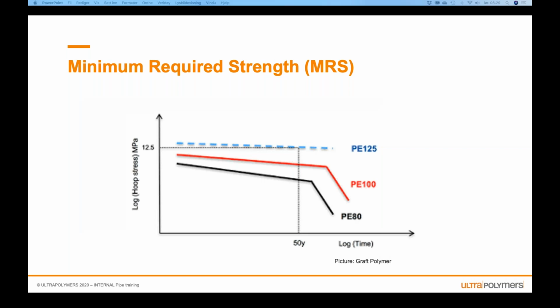So if you go into 50 years lifetime, you see what megapascal you have when you have this brittle failure. You go 50 years into the curve, you should only have ductile failures here. And then for PE80, you are at 8 megapascals or above. PE100, you are at 10 megapascals or above. And PE125, you are at 12.5 megapascals or above at the 50-year lifetime. So all pipes used in infrastructure in Norway should have a lifetime of at least 50 years. They want to have a lifetime of 100 years.